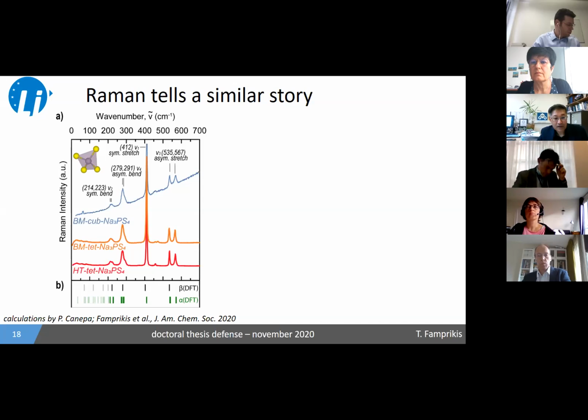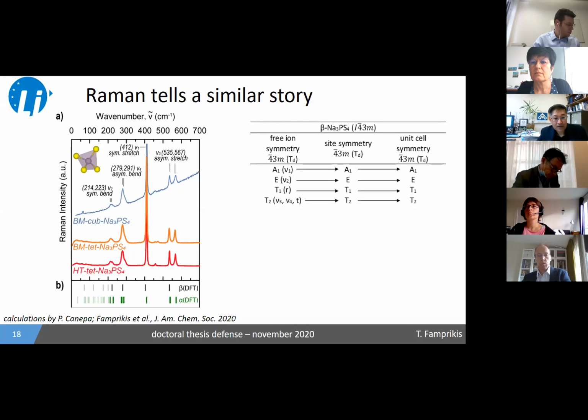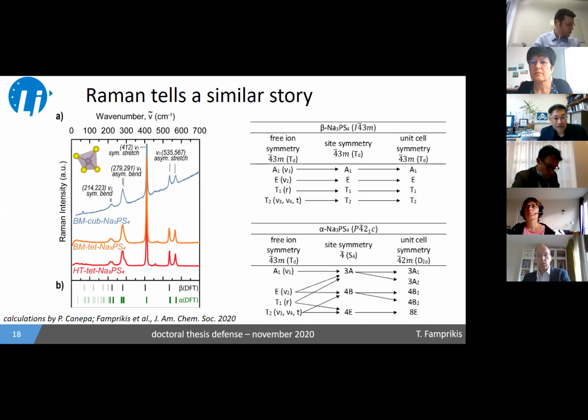And you can see basically that all the samples agree much better with the tetragonal model than the cubic model. And if you're curious a bit, the reason for that is basically that in the cubic model, the PS4 in the crystal structure actually enjoys the same tetrahedral symmetry as the free ion. So in that sense, there should be no splitting of the peaks. You should simply have 4 singlets for the normal modes. Whereas in the tetragonal space group, the site symmetry and the unit cell symmetry of the PS4 anion in the crystal structure are lower than the free anion.